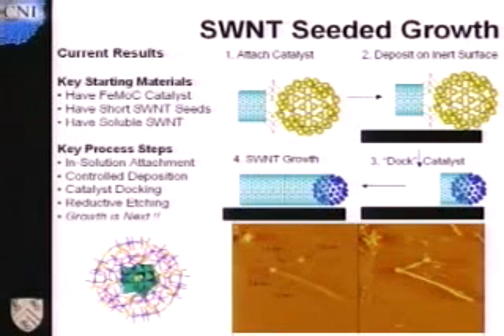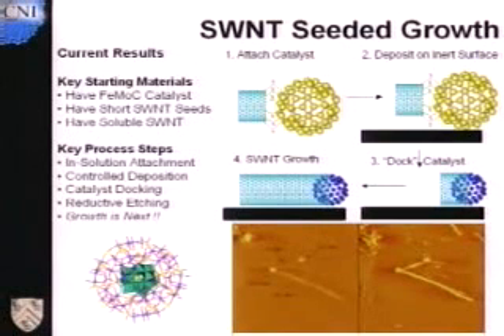So this should end up with a very much more efficient process with fewer byproducts and high purity. So this is a schematic of how we approach this. We call this the SWNT seeded growth program, in which we would start out with short nanotubes using a cutting process. We can take multi-micron length tubes and cut them down to 50 to 100 nanometer type seeds. And I'm not going to go into that.